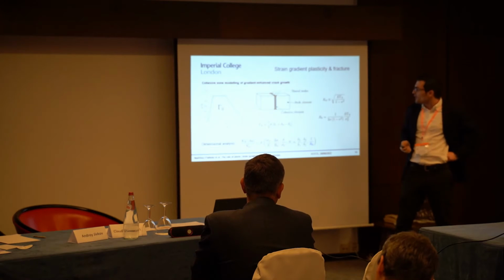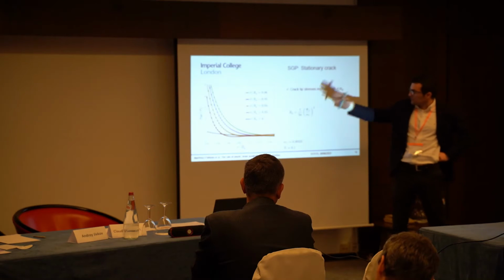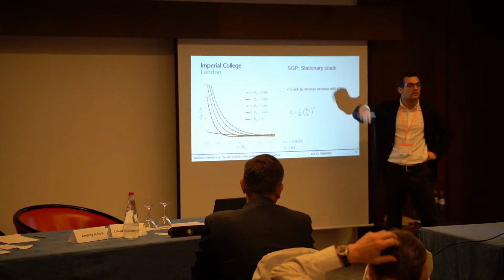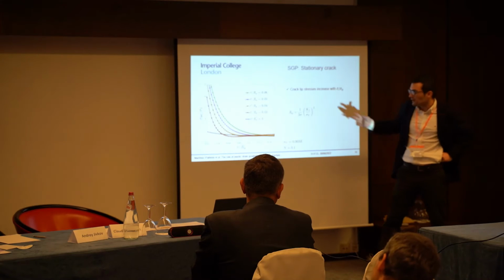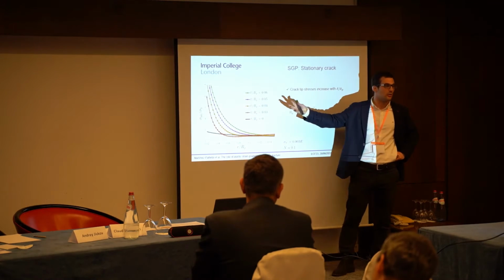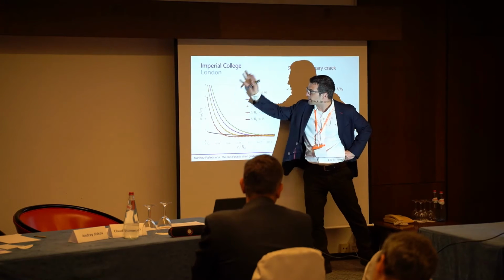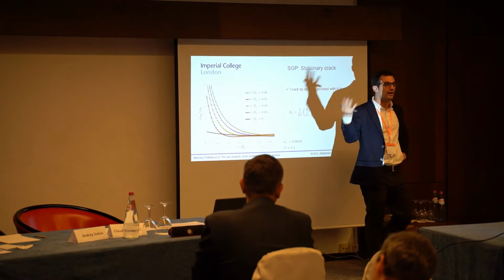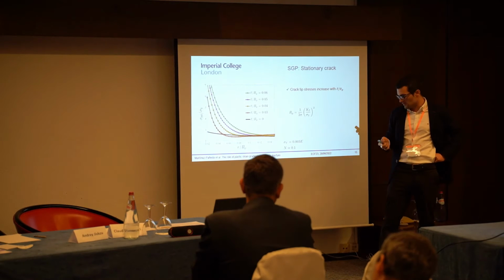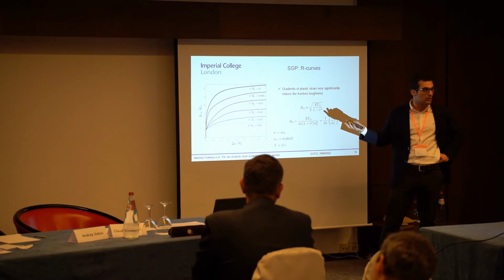So then when you simulate first the stationary result, so the crack is not growing, I'm just plotting the stress ahead of the crack. And here, as you would expect, you will see that as this ratio between the length scale and the plastic zone increases, you get a higher influence of these plastic strain gradients, you get higher strain gradient effects, so higher stresses. Then we model the crack growth resistance curves.